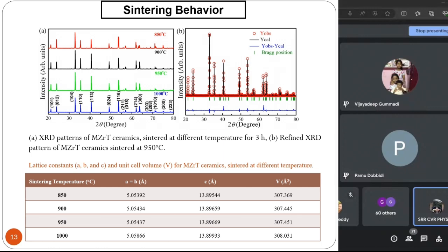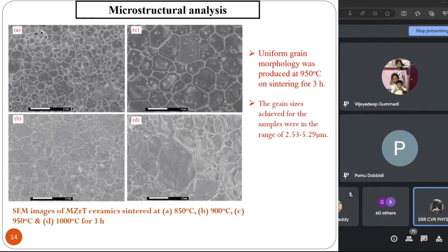Yes, sir. So now, if you see the microstructures, when I say density is good, what is the meaning of it? The compaction of the material will be very high. That means higher density means lesser porosity. You see that the material density is very high. So we have sintered at, as I showed you, 850, 900, 950 and 1000 degrees C. For the sample sintered at 950, you see a very good uniform microstructure, and there are no pores at all,